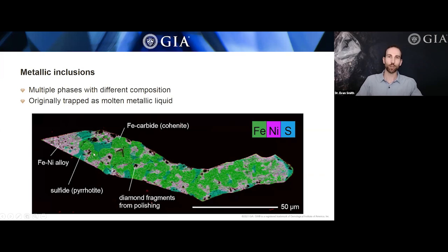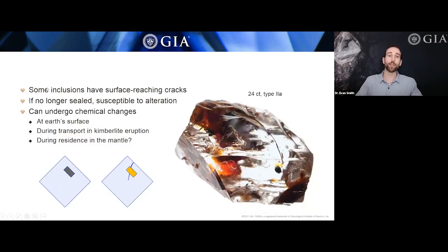And the interpretation is that this inclusion was originally trapped as a liquid. It was a molten metallic liquid. So I've spent a lot of time looking at inclusions like these, but sometimes you encounter inclusions that have a surface reaching crack in them. And what I mean by that is shown in this cartoon down at the bottom.